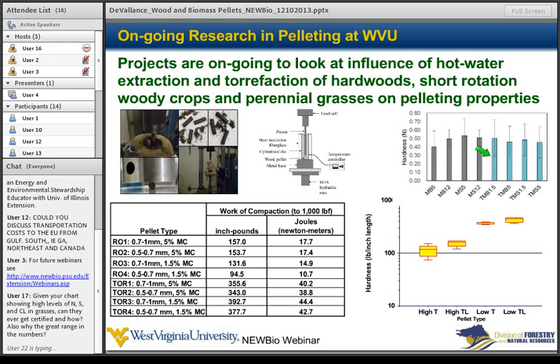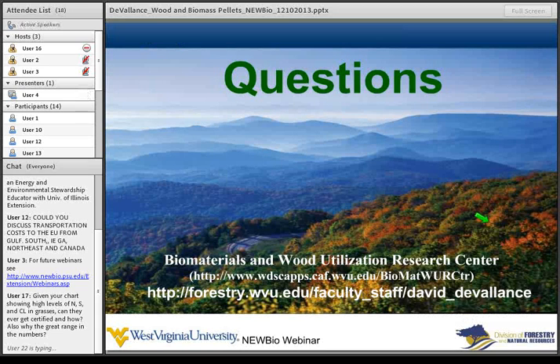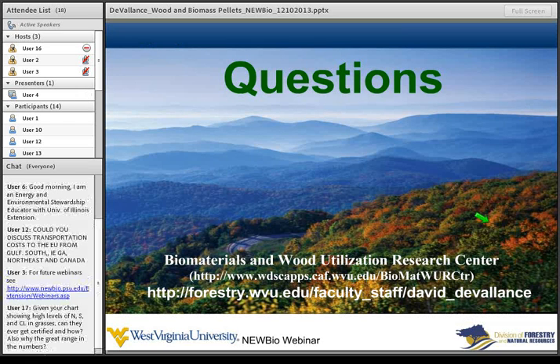And then this was on yellow poplar, I believe, looking at torrefaction levels of high and low, and with and without lignin added. You can see that the higher torrefaction level in this case had a little bit lower hardness than the low torrefaction level. Those are just a few examples of the things we have going on here, to add a little research context to this discussion.